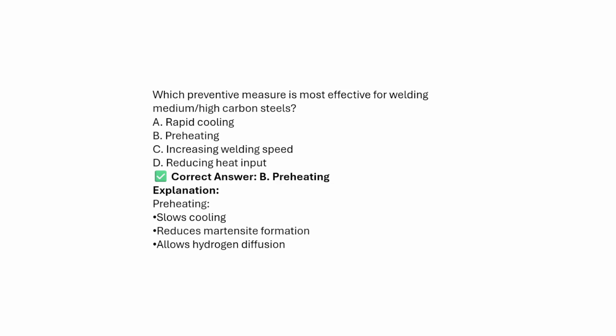Next, which preventive measure is most effective for welding medium and high carbon steel? Option A, rapid cooling; option B, preheating; option C, increasing the welding speed; option D, reducing the heat input. The answer will be preheating. Why? Rapid cooling means formation of much more martensite. Increasing the carbon content means hardenability will be more, which means much more martensite forms. To reduce the formation of the martensitic phase, what we can do is reduce the cooling rate.